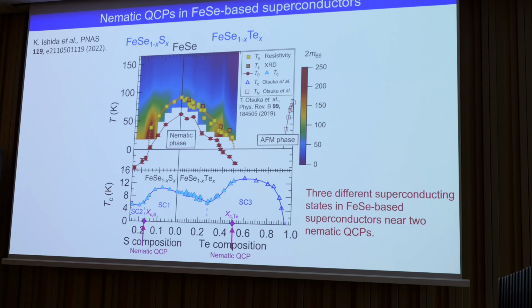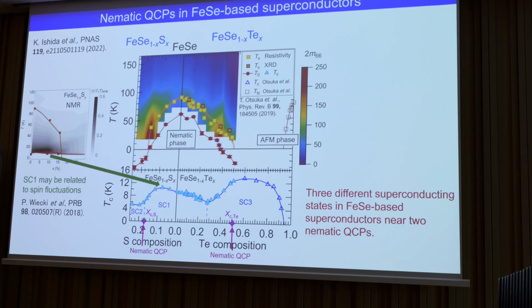That's already anomalous. Then, if you look at this SC1 dome, it turns out from the NMR measurements that this dome actually follows the amount of 1 over T1T in this phase diagram, which indicates that you have enhanced spin fluctuations, although we don't have any magnetic order in this phase diagram. So you have a kind of remnant spin fluctuations, peaked around 10% substitution. So this dome is likely related to the spin fluctuations, meaning SC1 may be related to spin fluctuation.